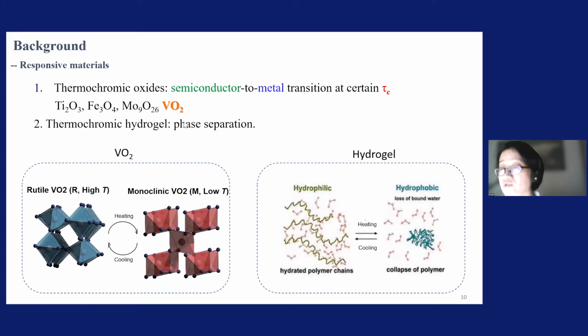First of all, start with VO2. VO2 is a thermochromic oxide, because it undergoes a semiconductor to metal transition at a certain temperature. There are quite a few ceramics that can have this semiconductor to metal transition. But why is VO2 so popular? If you read Science papers over the last 20 years, you will see a lot of VO2 has been published, simply because VO2 can change its phase from semiconductor to metal at only 68 degrees. 68 degrees means it is very close to room temperature already, right?